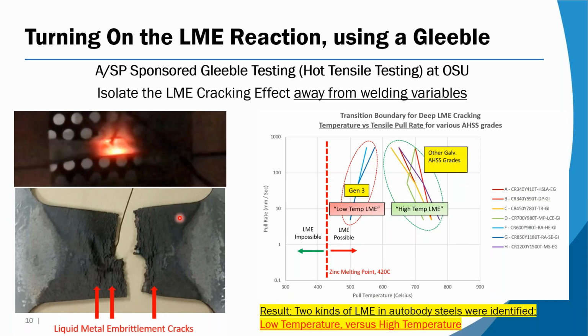Okay, so what does LME look like in a hot tensile test? This tensile sample here shows a lot of cracking in the sample, and that indicates the material's falling apart. If this same batch of material was stripped of the zinc - you just do a quick acid treatment and dissolve off the zinc - then these cracks go away and you have a nice hot taffy pull, with a lot of necking and so on, and you don't see any of these cracks. So it's pretty easy to look at the sample and observe whether you had LME or not.